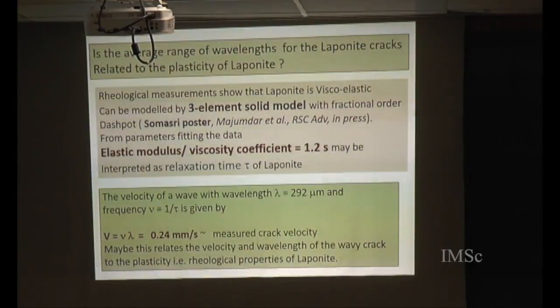So we thought that maybe the average range of wavelengths for the Laponite cracks, which is quite different from the average range of the perspex sheet wavelengths, can it be related in some way to the plasticity of Laponite? Now, from rheological measurements, I said that it has been modeled by using some standard viscoelastic technique. Only the special feature of our modeling is that a fractional exponent has been used in the equation for the viscous part, that means the dashpot equation.